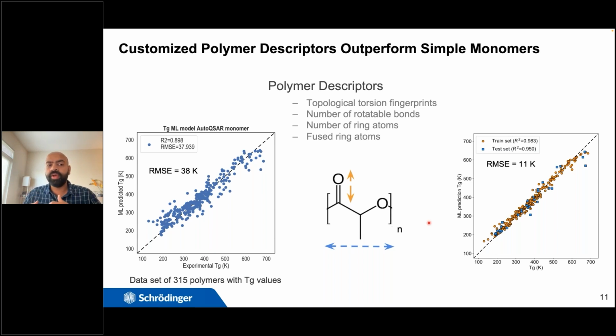But once we provide polymer descriptors, for example, the topological torsion fingerprints, which are a combination of substructure fingerprints that we normalize with respect to the polymer repeat unit, so that just because you make the polymer repeat unit longer, it shouldn't change the fingerprint, because we are talking about large molecular weight polymers. So the topological torsion fingerprints are normalized with respect to the polymer repeat unit. And we also add additional descriptors like the length of the side chain and the number of ring atoms, fused ring atoms, which influence the stiffness of the polymer chain. So if your polymer chain is really stiff because it has a lot of fused rings in the parent backbone, the Tg is going to go up. So we can construct those descriptors and add them to improve the model. And we can see here the RMSEs are around 11 Kelvin to predict the properties of these polymers.